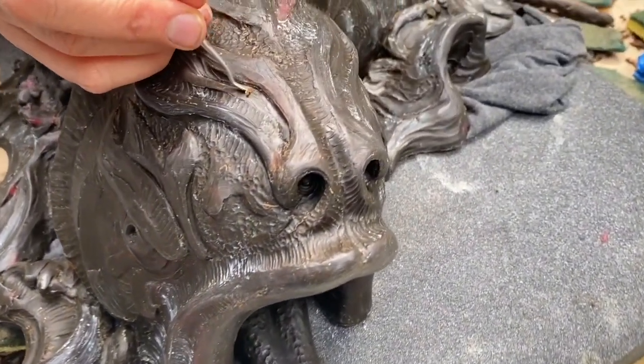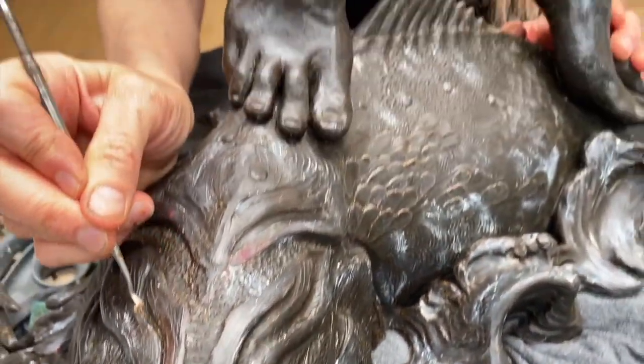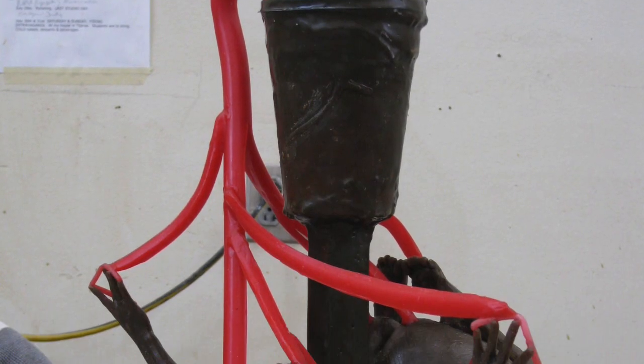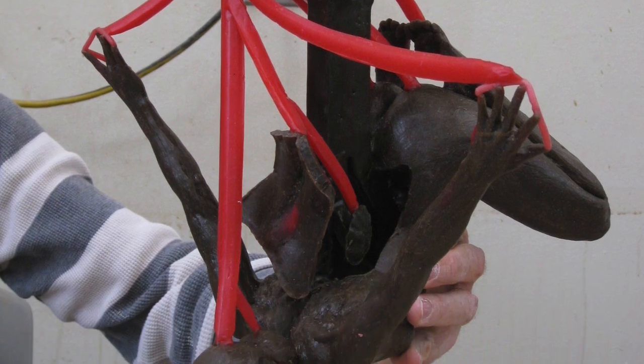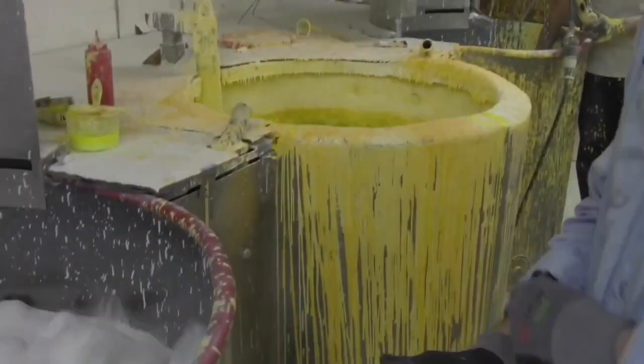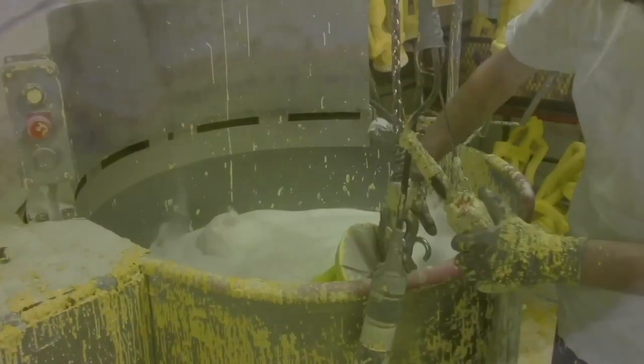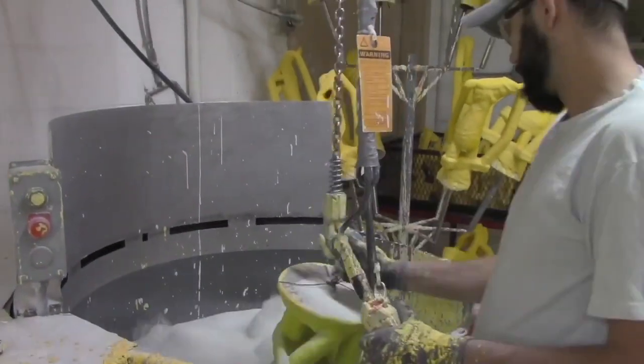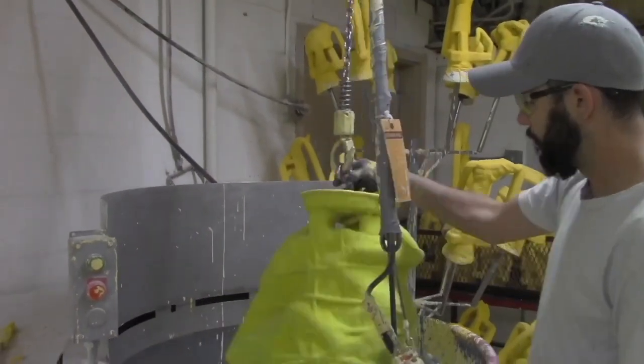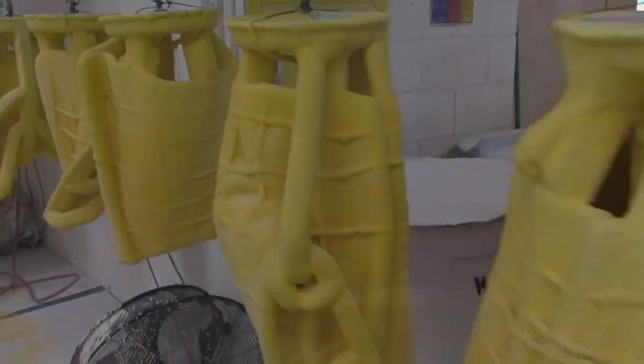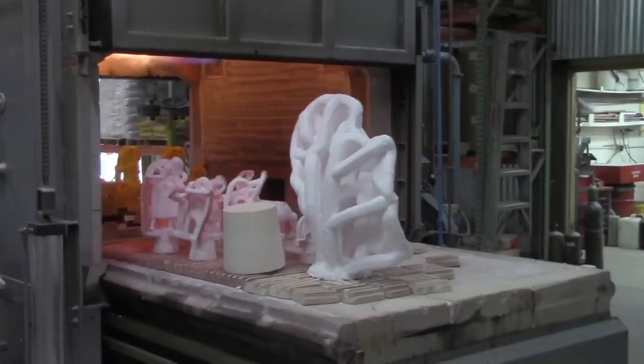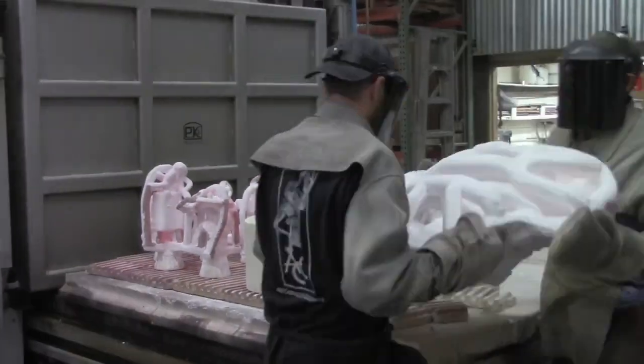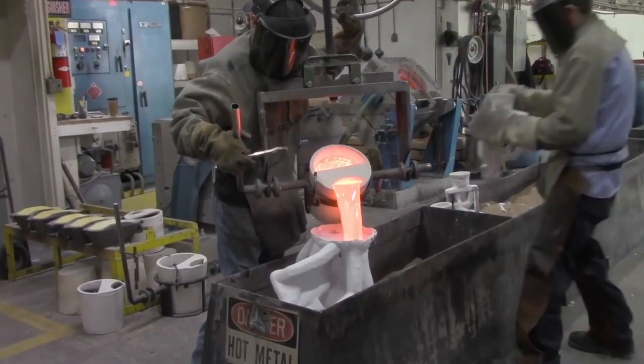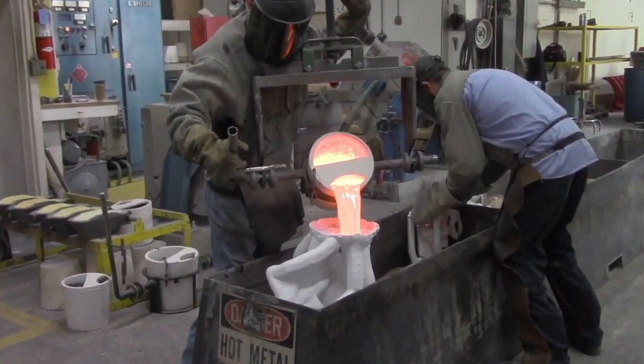The wax is then sent to our foundry, where they add wax sprues and gates, similar to what you see here, which will function as conduits for the molten bronze. This entire wax construction is then dipped in a liquid called ceramic shell, followed by sand. This process is repeated until a thick layer of shell is built up around all parts of the wax. This mold with the wax encased inside is put in a kiln. The firing both hardens the ceramic shell material and melts the wax out, leaving a void into which, voila, we can pour molten bronze.